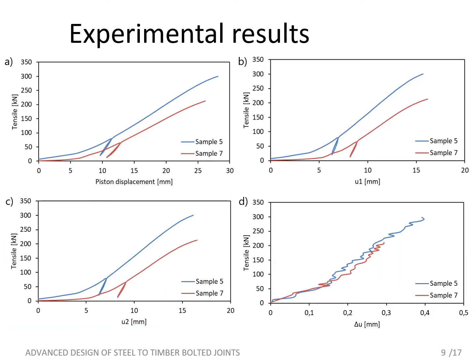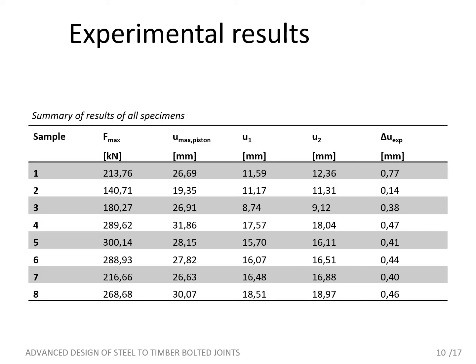These figures show the displacement of sample number 5 and sample number 7. Figure A shows the displacements of the piston. Figure B, measured point 1, figure C, measured point 2, and figure D, the difference between them. The measured values for all test specimens are given in this table. It is important to mention that some complications occurred with sample 1 and 3 during the test experiments.